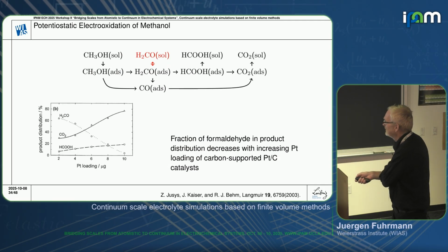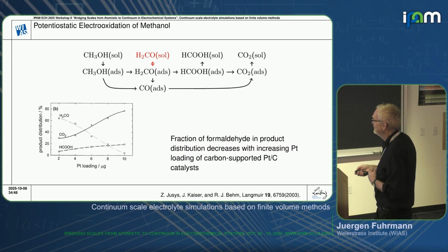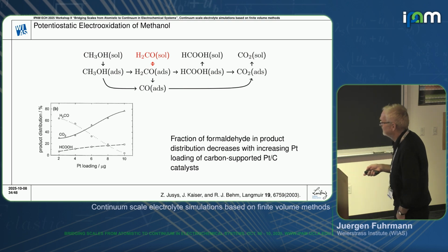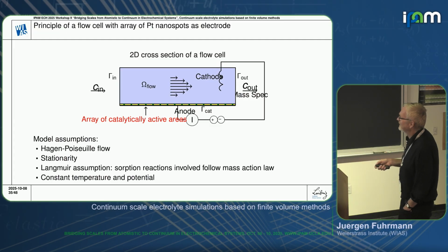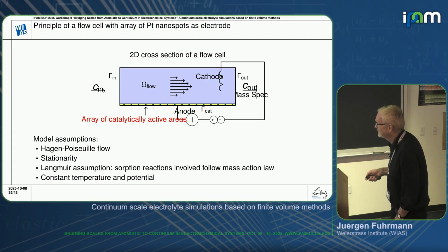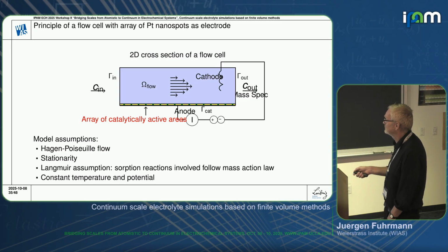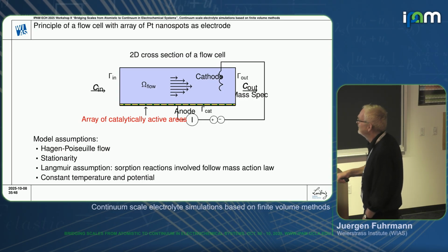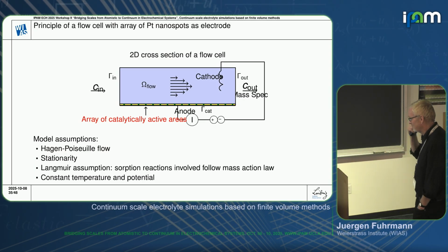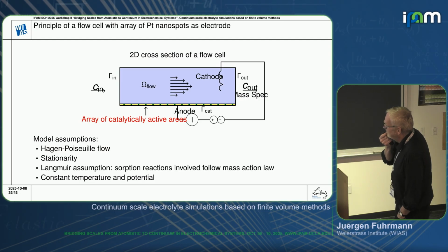And there's another experiment, also with formaldehyde, which is similar, which relates the rate of the intermediate product also to the loading of the catalyst. And this raised us to make this type of experiment with this kind of reaction boundary conditions in two variants. One would be that we have one large catalyst area with a given length, or a given amount of catalyst spots, where species could desorb at one spot, are transported to the next one, could react again, and so on, and this could go on.